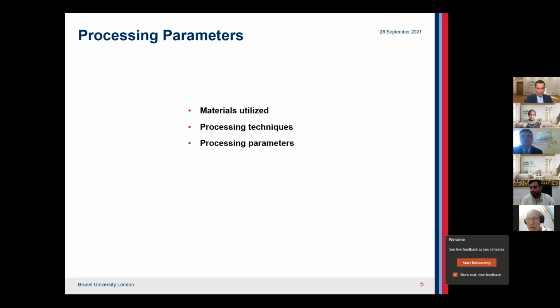So as a benchmark or as a start, since most of the composites are being developed through compression molding to develop either cladding or decking panels, I have investigated the effect of processing parameters on developing date palm fibers with polyester resin. The main reason for me using polyester resin is that I have investigated different thermoplastic composites. I wanted to minimize the amount of machinery or equipment that I need to use in order to develop a composite. So using a thermoset enables me to use a hand layup technique in the beginning, and then hot press the material in order to develop the final product.